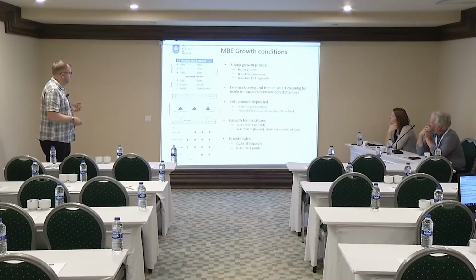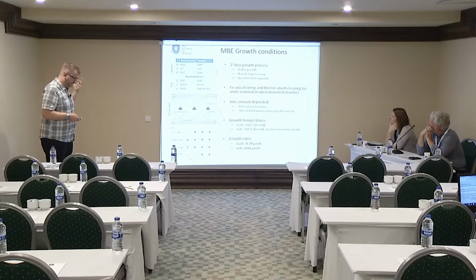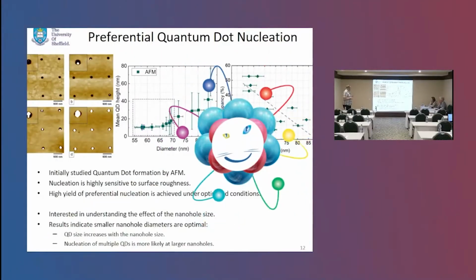So I've already described this part of the diagram, how we're going to do the etching. This is just the layer structure itself, so we have the sacrificial AlGaAs layer in that structure. And we do a lot of ex situ cleaning, using chemical cleaning and then trying to strip off the resists with organics and so on. And then in situ we do hydrogen cleaning to remove the native oxide before transferring in the AFM, where we have a couple of places with dots.